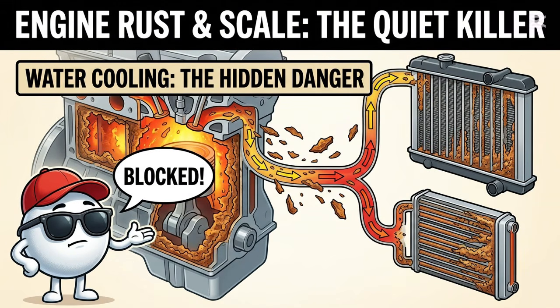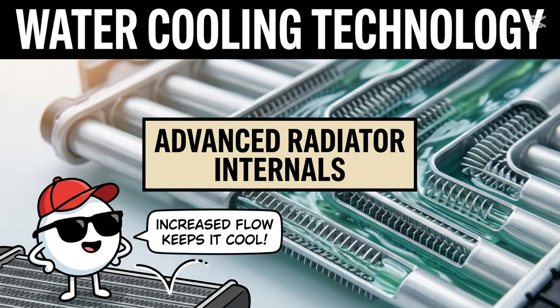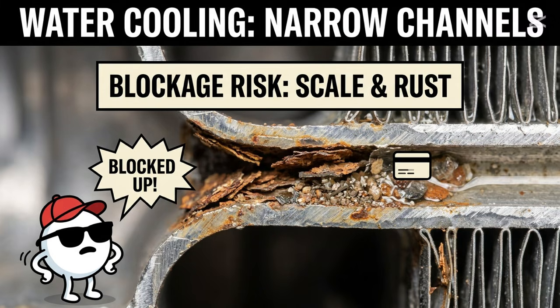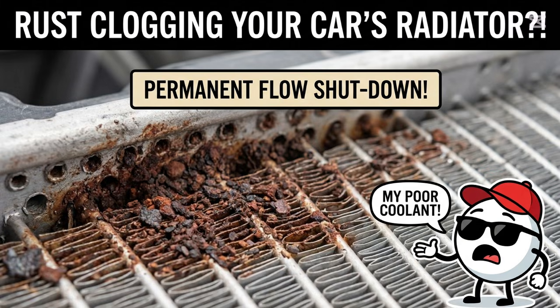As that scale continues to build and eventually flakes off the hot engine walls, it doesn't just disappear. It travels directly downstream into your primary heat exchangers, the radiator and the heater core. Modern radiators are built with ultra-thin aluminum tubes lined with internal turbulators, tiny fins designed to maximize surface area and keep the fluid turbulent for better heat dissipation. These channels are narrow, often no wider than the thickness of a credit card, which makes them extremely vulnerable to blockage from floating scale particles and dislodged rust flakes. Within that same 24-hour window, dislodged scale and rust migrate into the top tank of the radiator and start lodging in the entrance ports of those microchannels, permanently shutting off coolant flow through entire sections of the core.